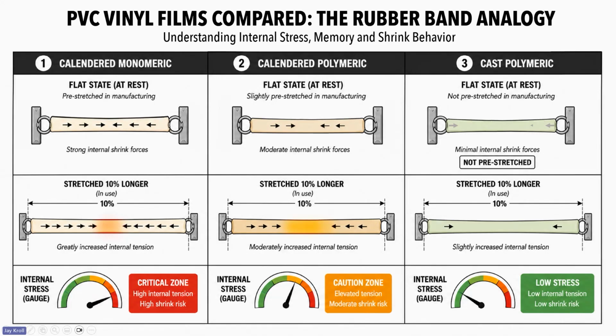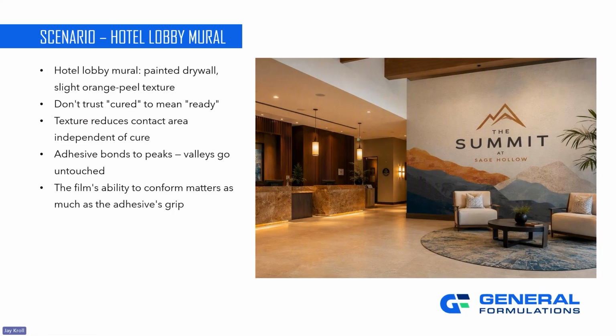Back in the Surface Intelligence webinar, we used the example of a mural in a hotel lobby. It was painted drywall with a slight orange peel texture, and they expected it to hold for 3 to 5 years. The paint is flat finish and dry to the touch. And we look at that, and okay, texture, that's one thing. We need to think about that. It changes that adhesive film contact math, right? With a rigid film, the adhesive's only touching the peaks, not the valleys. So the contact area is reduced regardless of what the paint is like.